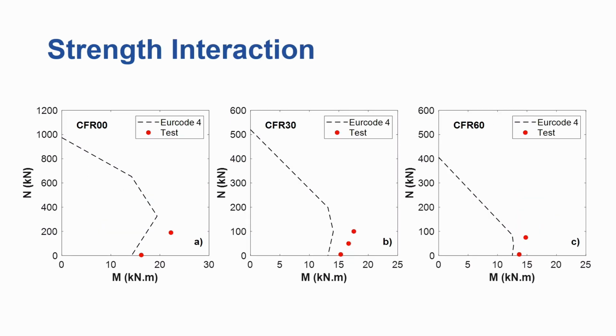Then we looked at the strength interaction. So we looked at Eurocode 4 provisions for a member subjected to uniaxial bending with a coexistent axial load. And we noticed that the test results here fall inside the Eurocode 4 axial load moment interaction curves, indicating that the code is quite safe for such members, in fact, a bit conservative.